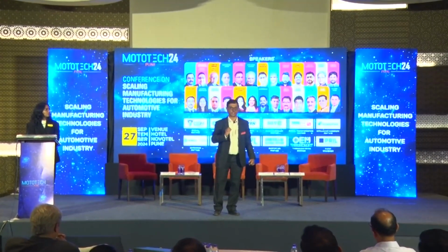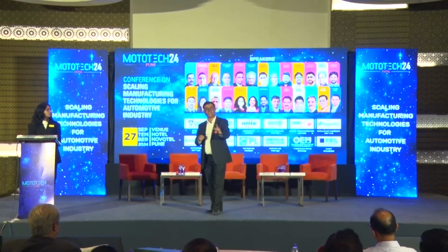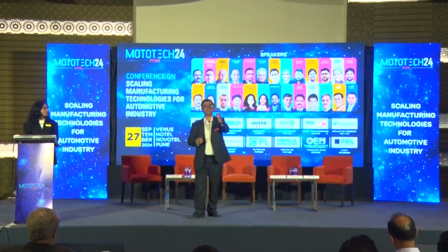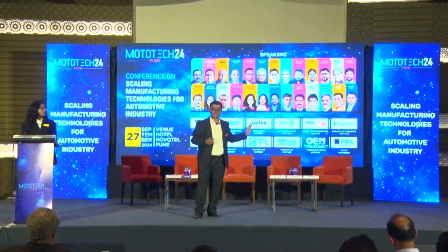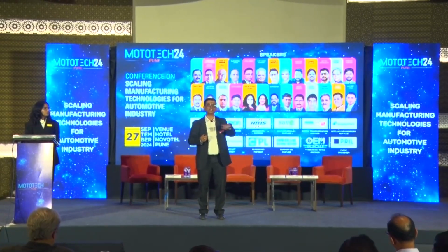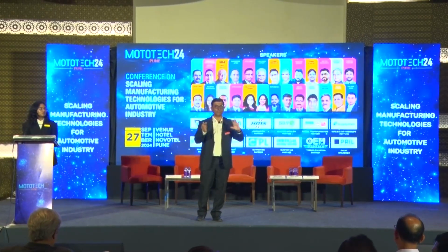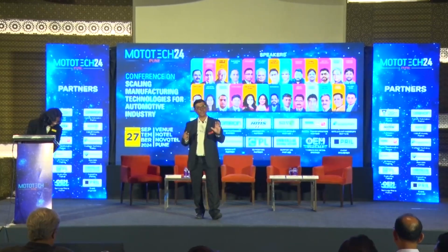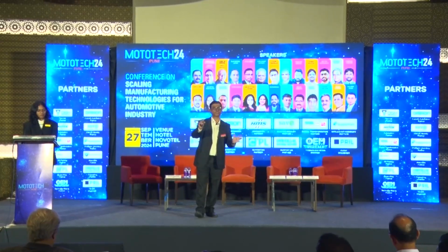For end parts, toolings and all, they require high accuracy. Out of the machine, from Stratasys machines I'm talking about, we are talking about 100 microns accuracy. We have technologies which will give you 50 microns out of machine accuracy. In certain cases, some customers need 10 microns accuracy. So they use our technology, which gives 50 microns, put the same component on a machine, and take one simple cut, which will give them 10 micron accuracy. You can put this on a milling machine or a lathe, absolutely no problem. But out of machine, you get either 50 or 100 microns, which is fairly good enough for most components.